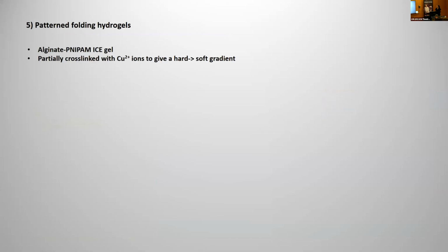Now, based on what I was speaking about before with copper ions being used to cross-link polysaccharides, instead of just fully cross-linking the whole network and having it shrink, like that previous one I showed you, it was completely shrinking in every dimension, we can control that shrinkage by having just some parts of the gel cross-linked more than others. So let's show what I mean.